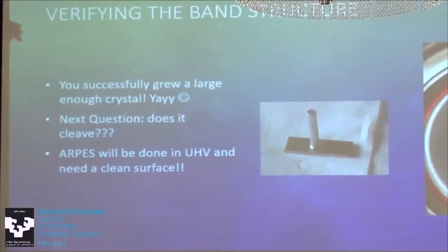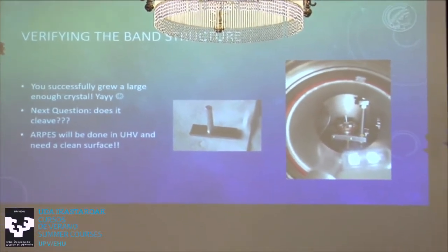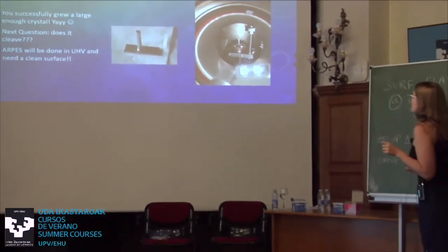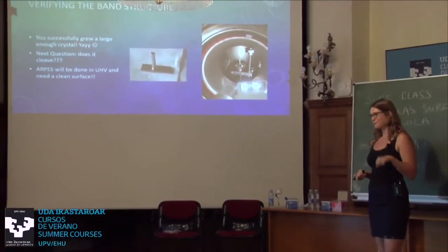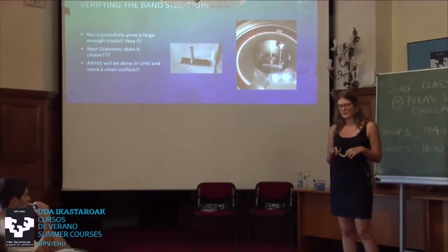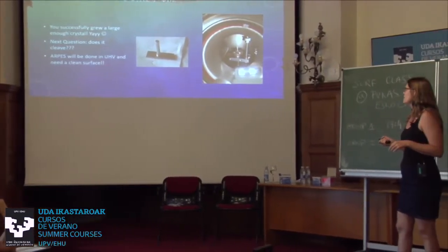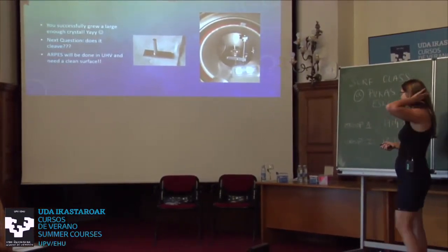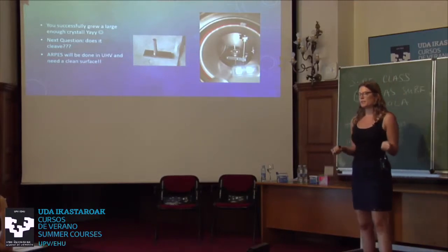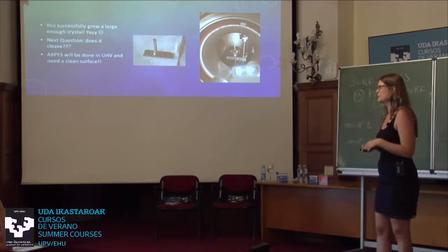Okay, so now we grew our crystals. So let's say we identified a material we care about. We grew the crystal. We can be super happy we have a large single crystal. Well, the next question is if it's actually going to cleave. Because I predicted materials before, and I grew materials, and then nobody could cleave them, and that's a problem trying to publish about it. So if you want to do ARPES or STM or any of the surface-sensitive methods, you need to cleave your crystal in UHV, because you need to have a perfectly clean surface for the experiment.